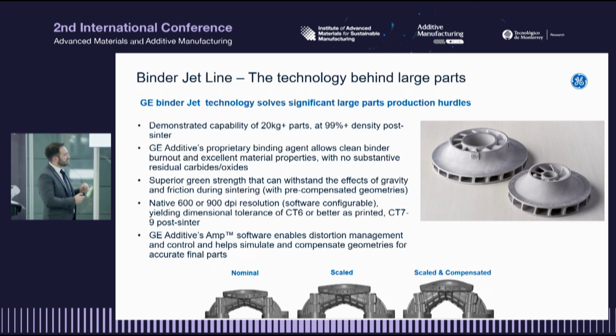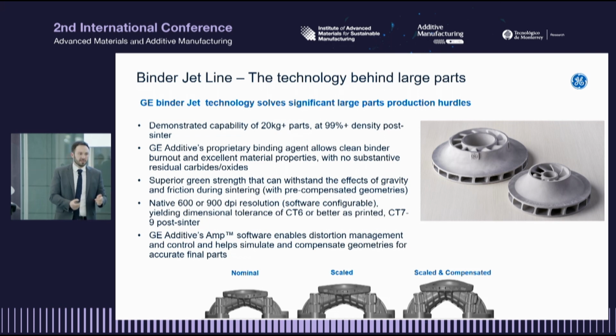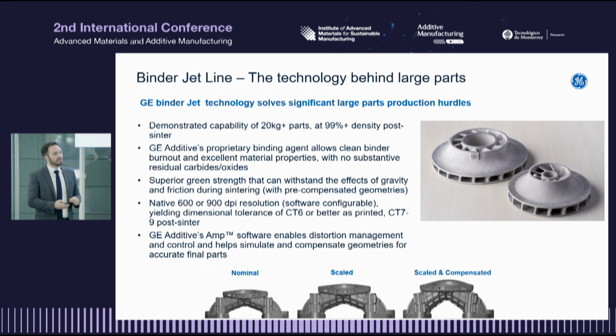On the bottom side of this, you can see that manifold that I held up earlier as the AMP example. The takeaway from this one is that we didn't design this for trade shows. We designed this because a colleague of mine needed a new manifold for his Honda motorcycle. We didn't expect it to fit the first time, and it turns out we needed to compensate it. But after the fact, it fit right on. After printing and after sintering, if you're familiar with sand casting, we get to CT7 and CT9 levels of fidelity and tolerance on these components. So as promised, a binder jet replacement of castings, the tolerances are already there.